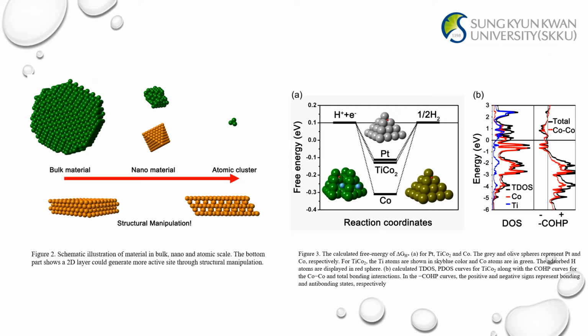As we can see in figure 3, it is a theoretical calculation of platinum metal, our materials, and cobalt metal. It is clear that the free energy of hydrogen on the TiCo2-rich materials is very close to that of platinum metal. It means that it may have extraordinary performance in the hydrogen evolution reactions.